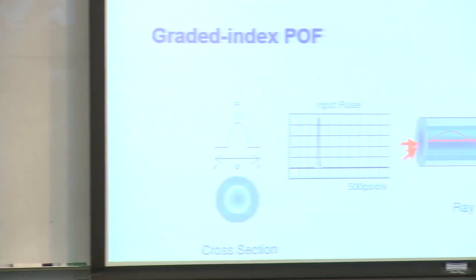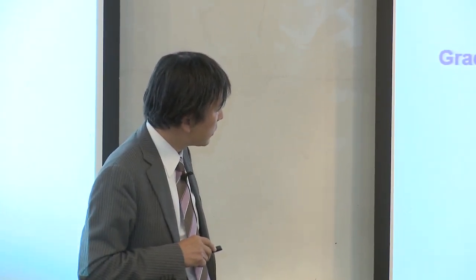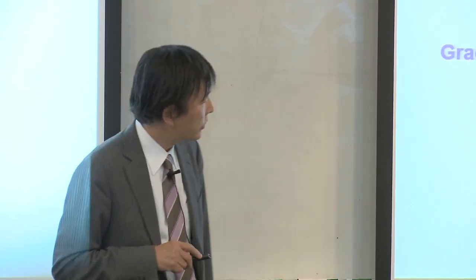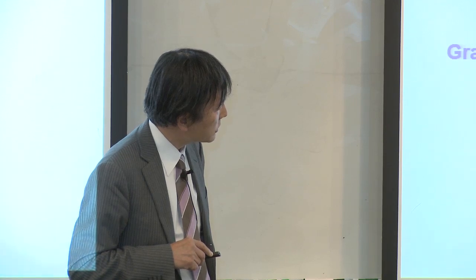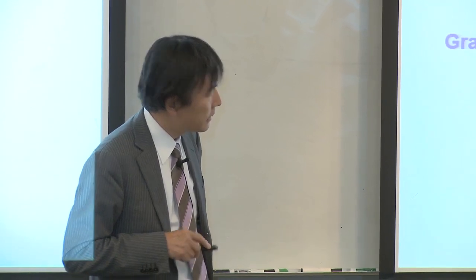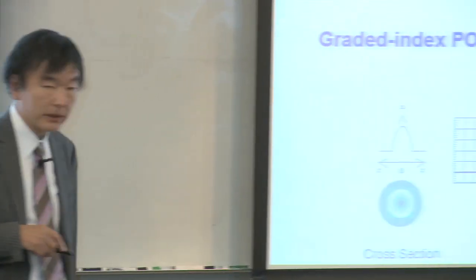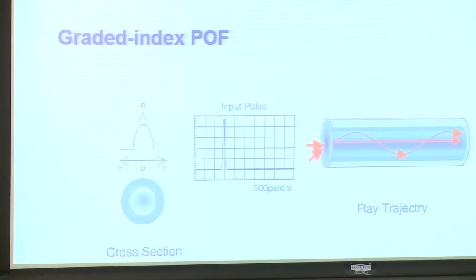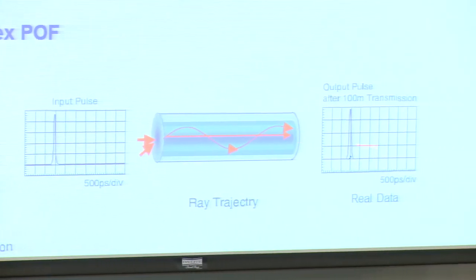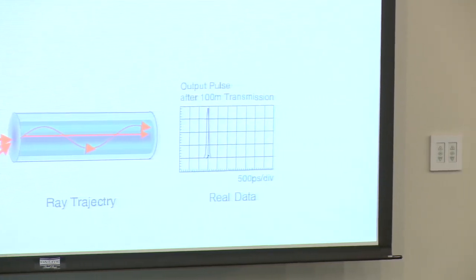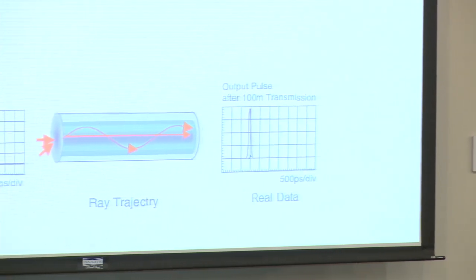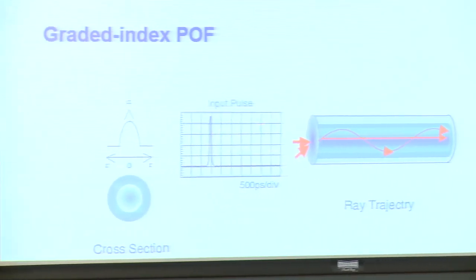The light going straight at the center has the shortest path, but always goes through the center with the highest refractive index. So this light has the slowest velocity. On the other hand, the light with sinusoidal trajectory has a longer path compared to a straight line, but very often goes through the periphery region with lower refractive index. So the average velocity is faster than that of light going straight. So these two opposite effects are completely compensated when the refractive index profile is optimized.